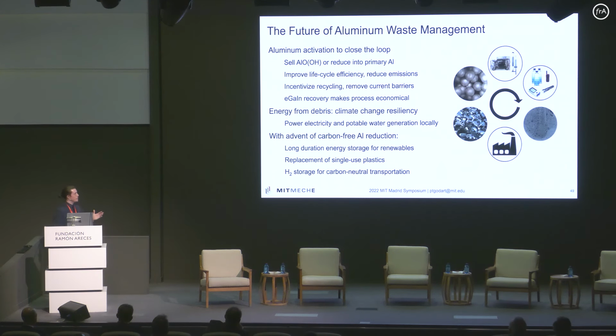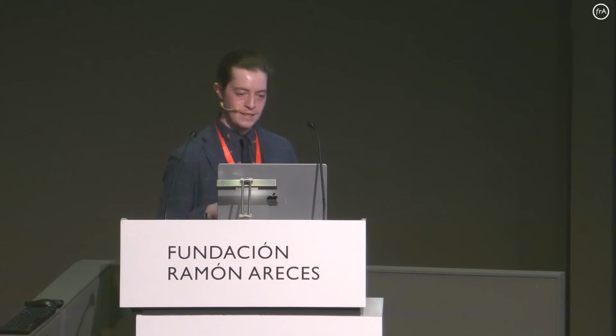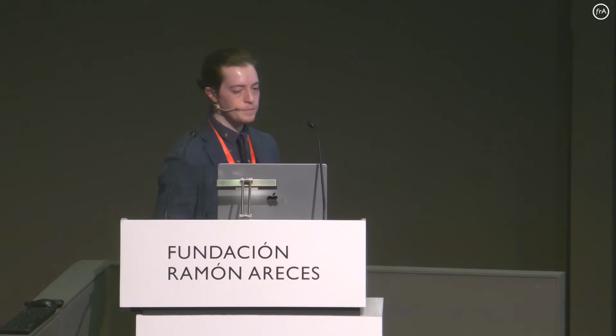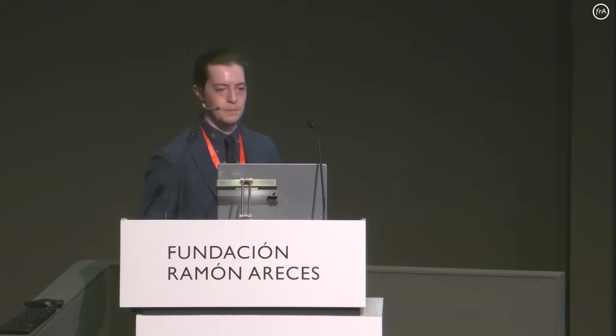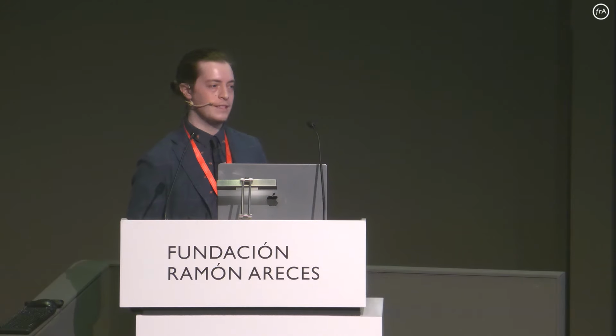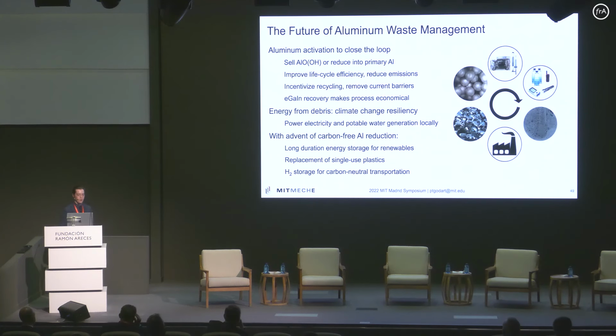So tying this all together, the future of aluminum waste management could be that we use this aluminum activation technology to help close the loop. We can take aluminum at the end of its life cycle, turn it into aluminum hydroxide, extract that energy back out, and then put that aluminum hydroxide back into the smelting industry where we turn it back into primary aluminum. This improves the life cycle efficiency of aluminum and helps to reduce emissions associated with mining. That's today. It would also incentivize recycling and remove some of those current barriers. And this is all possible due to that gallium indium recovery. So you'd need just a small amount of this gallium and indium to begin with, and then this is a closed cycle from there. That's just taking in aluminum and water.